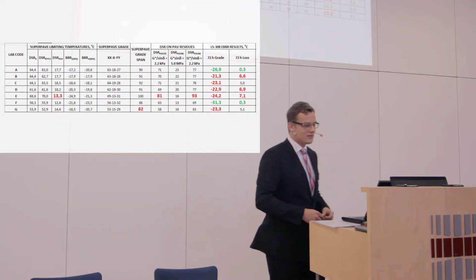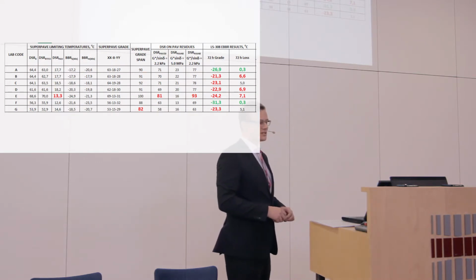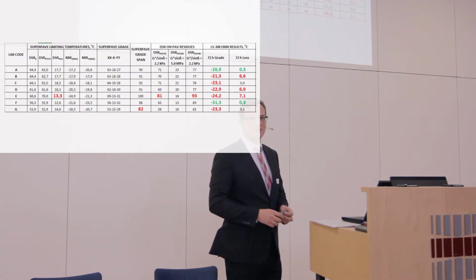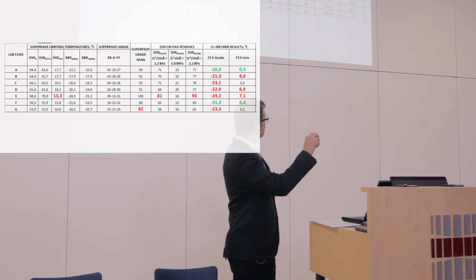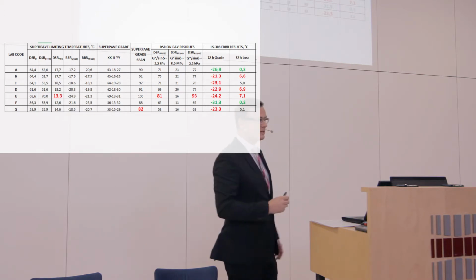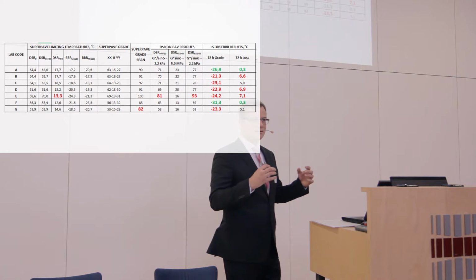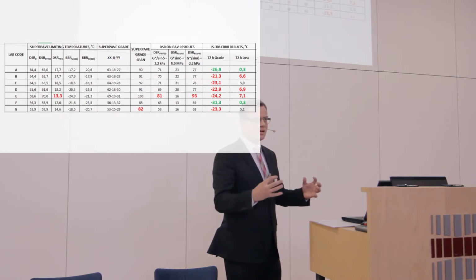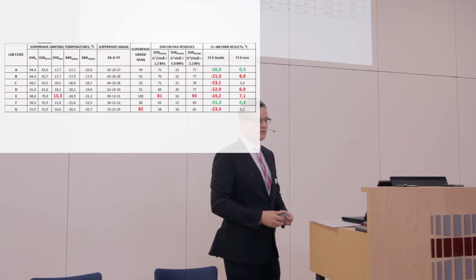As you can see, there are two very good binders that don't suffer any physical hardening. So with these binders, A and F, you can be confident that nothing happens during the time - there's no isothermal processes going on that could damage this asphalt.